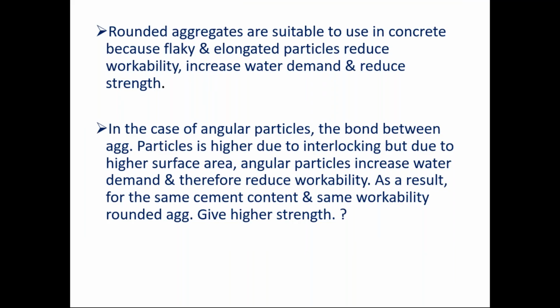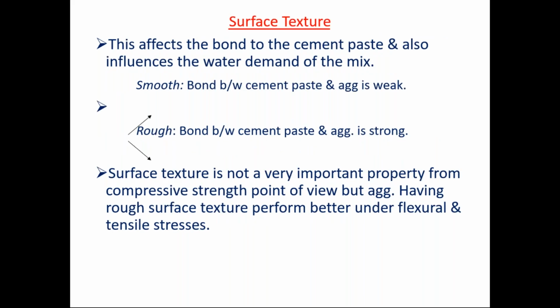Rounded aggregates are suitable to use in concrete because flaky and elongated particles reduce workability, increase water demand, and reduce strength. But in the case of angular particles, there is bond between the aggregate particles due to interlocking, but due to higher surface area, angular particles increase the water demand and therefore reduce workability. As a result, for the same cement content and same workability, rounded aggregates give higher strength. So this is how you can see the difference between the rounded aggregate and the angular aggregate.